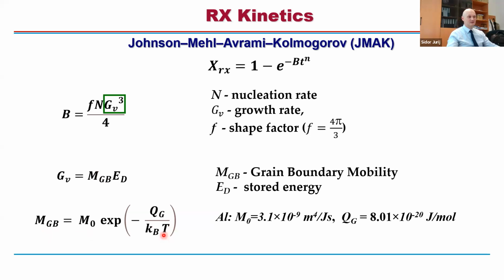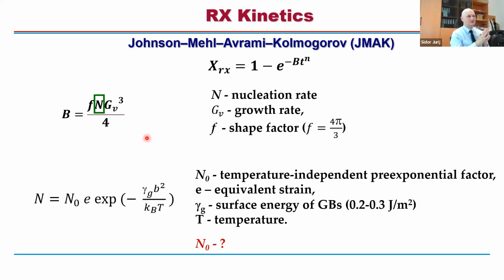So you should know the activation energy, temperature, you know. So if you put, for instance, those parameters into your equations, you can calculate the mobility. At least we can calculate G_B. Okay, f now is a shape factor, that's okay. And then the question is how to calculate the nucleation rate N. Okay, N in fact is defined as N0. Here you have the surface energy of grain boundaries, Burgers vector, temperature. You know, k is a constant, okay, it's the Boltzmann constant. However, the nucleation rate depends on the strain, right? So sometimes people multiply it with strain or strain rate, or they use some normalized values. Okay, in our analysis, we simply multiply it by strain. But the question is how to calculate this N0.